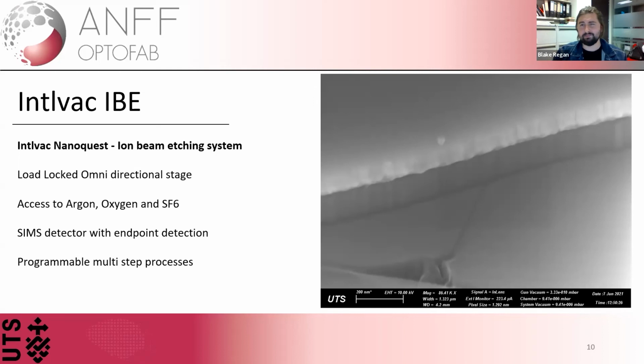I believe some of the best papers I've ever seen still barely breach the 50 nanometer area. But depending on your ability to fabricate, and that's specifically on top of diamond, by the way, where diamond is an insulative material where you get secondary electron exposure onto your EBL, which can give you a little bit of an edging effect to the base of your structure, which is why we had some imparted roughness on the side of our mask in the first place.